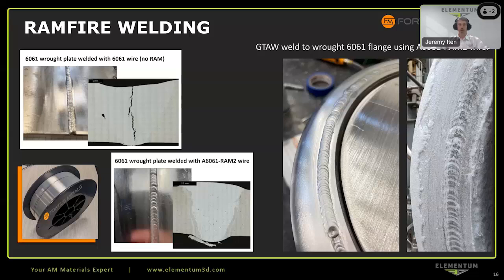So what we did is we used now our RAM reactive constituents in a wire that was produced by our partner, Fortius Metals. And you can see a spool of that wire in the bottom left. And now we were able to take 6061 wrought plate, weld it with this 6061 RAM2 wire, and avoided that cracking problem. So this concept was then used for welding the manifold to the printed DED nozzle. So a TIG or gas tungsten arc welding was used to weld the flange with the wire, and you can see the weld that formed was very, very nice looking, very high quality, and it held up well in the hot firing as well.